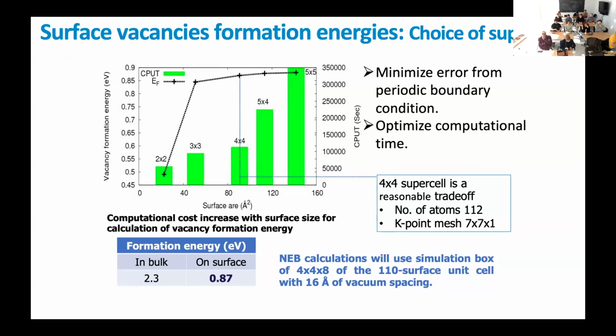So the main properties, including the magnetic properties. And then, if you are dealing with vacancies, or you want to look at the effect of defects on carbon adsorption, in this case you will have to conduct some studies to look at the effect of the finite size on that. So you will see here, for example, if I take a 2x2, and I will show you what it means, 2x2 iron slab, okay, and 3x3 and 4x4 and so on and so forth.